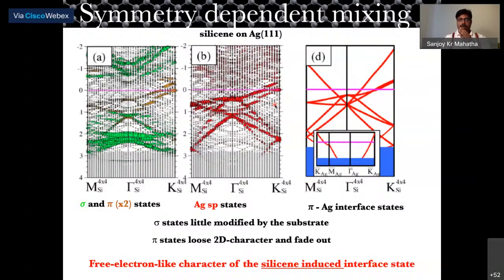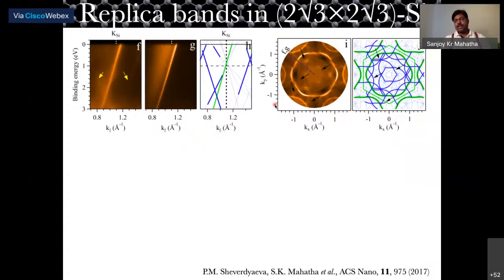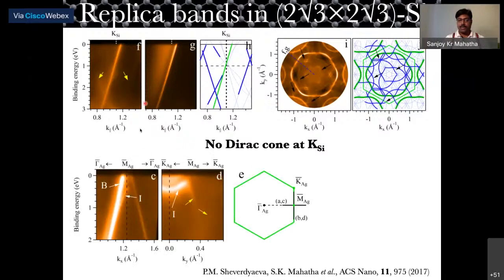And we did the same thing on 2 root 3 by 2 root 3 structured silicon, which was grown at a different temperature, at 270 degrees centigrade. And we saw a similar kind of thing. There was no Dirac cone at the K point of the silicon, and there was also no Dirac cone at the M point of the silicon. It's the same thing. You see a parabola with a maxima along this direction and a minima along the orthogonal direction. And so there is no Dirac cone at the M point also.